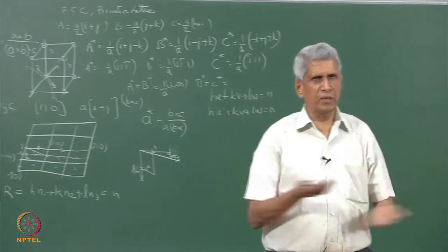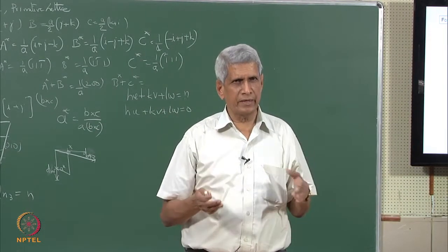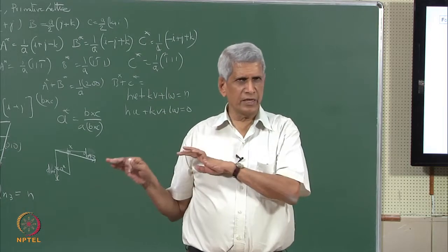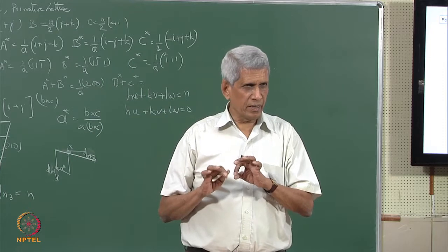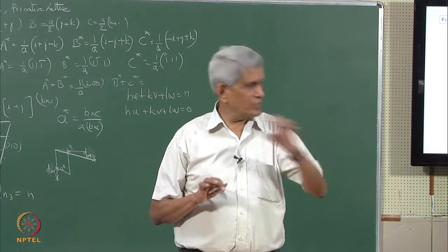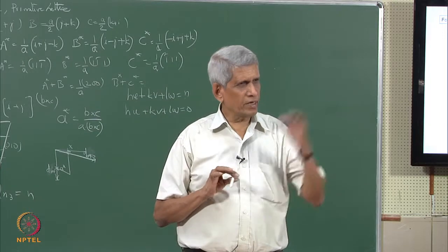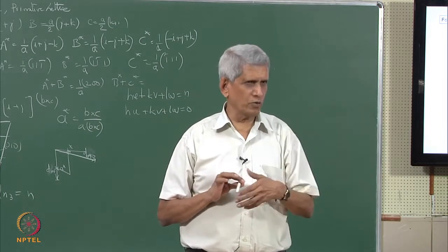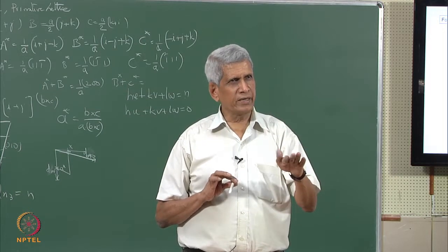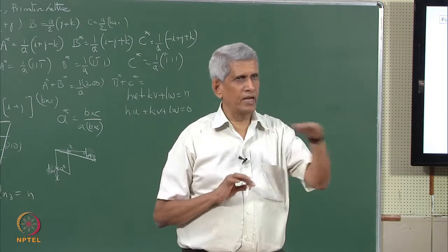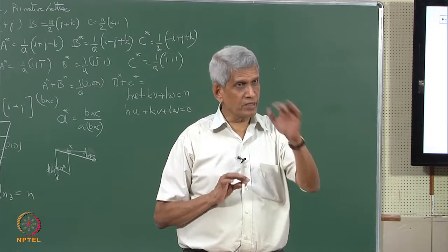When we get the diffraction pattern, analyzing the pattern, generally what we get in a normal diffraction pattern is only the 0th order. But if we change the camera constant, which I will explain later, we can get information about the higher order Laue zones also. That means that in a single pattern, we can get various reciprocal lattice sections.